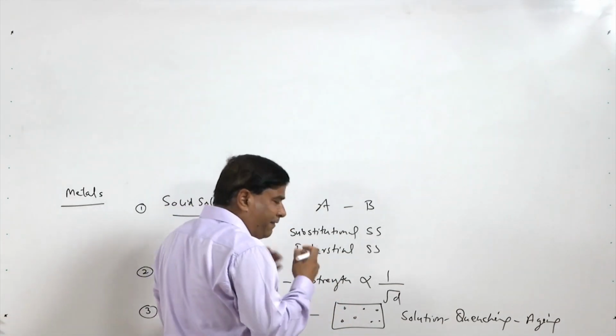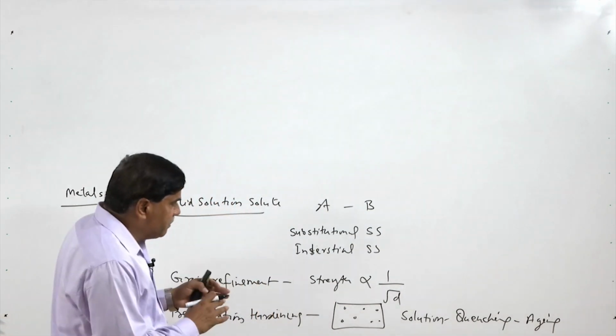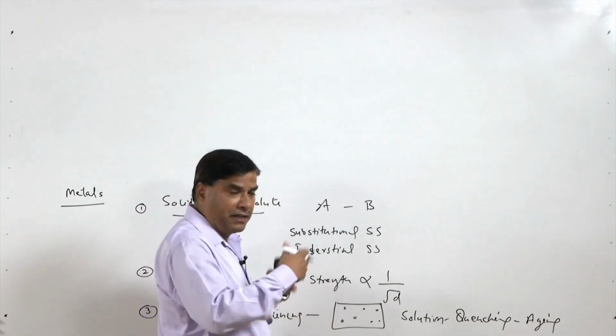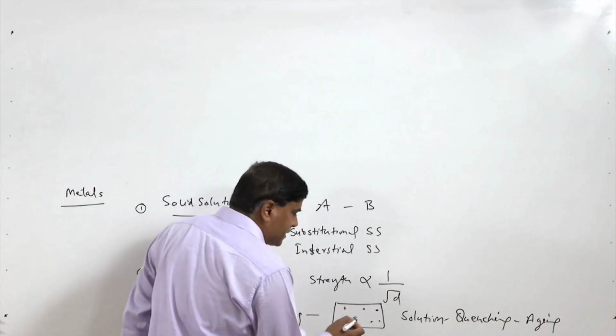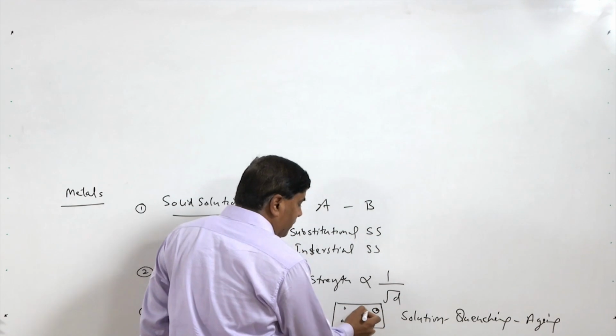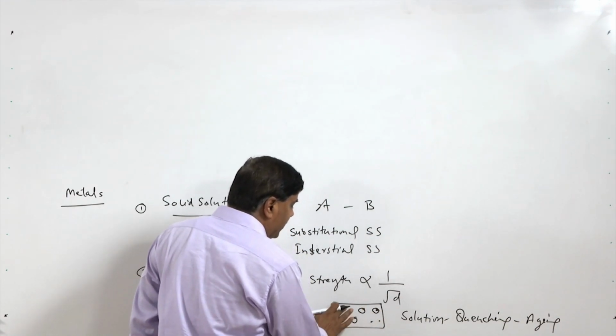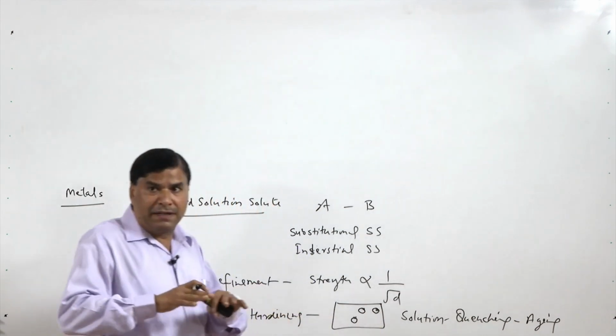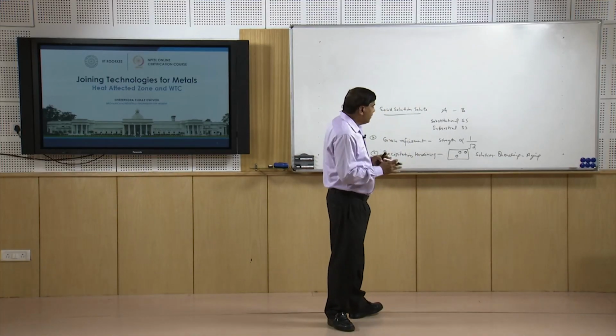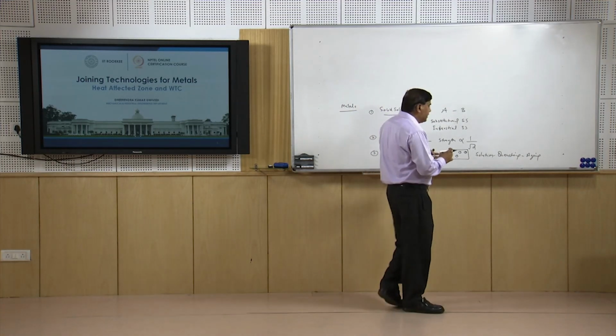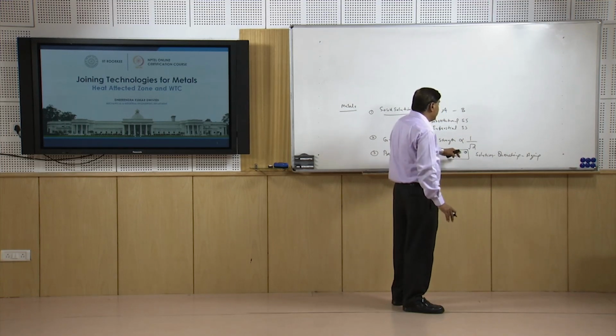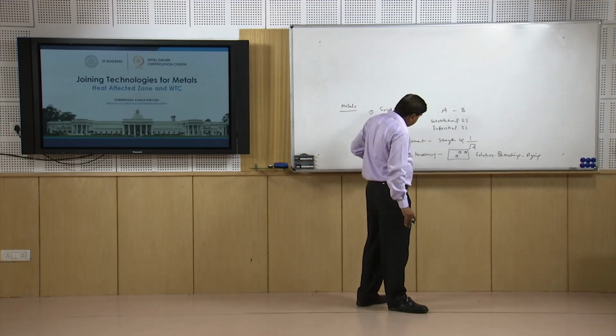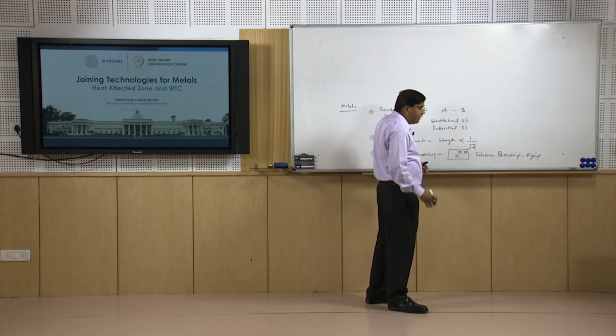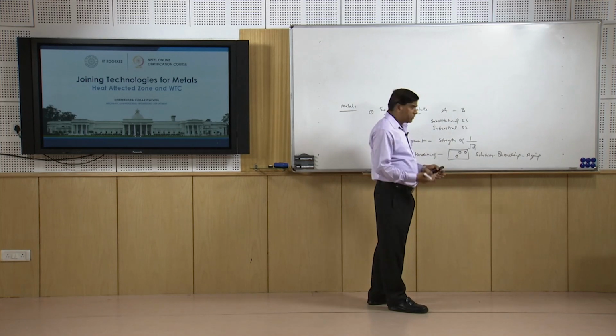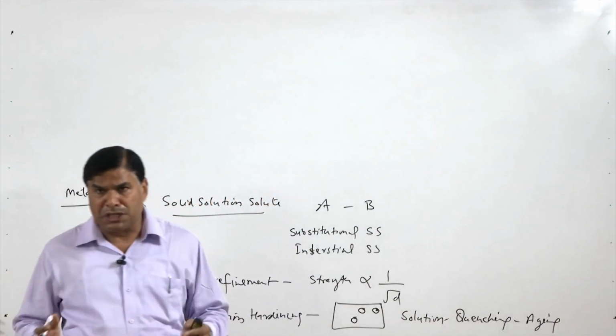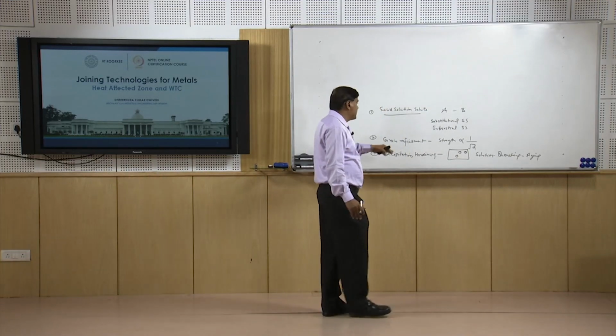So, whatever factors lead to enrichment or an increase in the number of precipitates will strengthen the material. Otherwise, whatever factors cause coarsening of the precipitates or their dissolution, there are two aspects: either the precipitates get dissolved in the matrix or they get coarsened. Both these factors, due to the application of heat, will lower the strength, because these metal systems get their strength from the precipitates, and whenever external factors like the application of heat cause the precipitates to either coarsen or dissolve, the metal gets weakened.